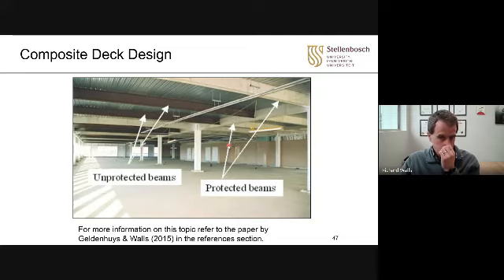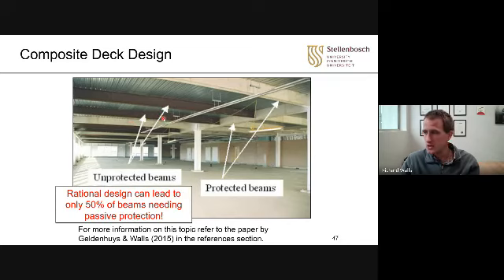So for instance, in this structure here, column beam, this shows you where the secondary beams are not protected. And so this would lead to quite a significant savings, because maybe you have 50% of beams, and the cost of this passive protection is high. So your client's going to love you if you can knock half the cost of the passive protection off your beams. But you would need to make sure your beams, slabs, columns, the white ones here are strong enough. So you design those and leave everything between.